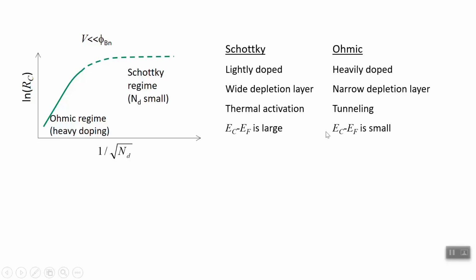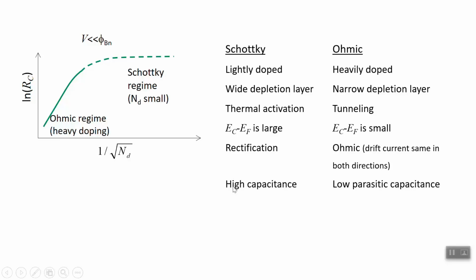The difference between the conduction band and the Fermi energy is large for Schottky, but we're degenerately doped, so it is small, actually close to zero, or you try to get it as close to zero as possible for an ohmic contact. So the Schottky barrier diode provides rectification. What that means is one-way conduction. It's a diode. As opposed to an ohmic contact, which is ohmic, it's not a diode. It functions like a resistor. Regardless of the direction of the flow, you will get the same current. So it's ohmic in nature as opposed to rectifying. The Schottky barrier has a lot of capacitance to it, and we talked a little bit about it. We're going to talk about it a lot more as we go into MOSFETs. And ohmic contacts ideally have low or no capacitance, but what capacitance is there is parasitic, which we're also going to spend some time talking about.